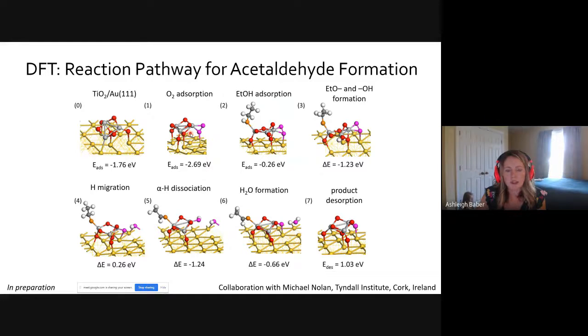And also, the literature shows that having molecular oxygen adsorbed at the interface between titania nanoparticles and gold can certainly make a difference in reactivity. And so you can see that O2 adsorption is modeled at the interface here. And then ethanol adsorption is on the titania nanoparticle.